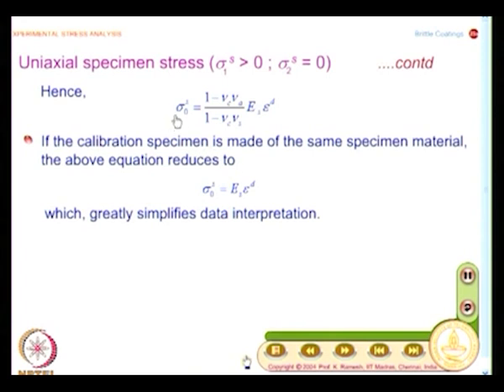So, what you have here is sigma naught s is equal to 1 minus nu c nu a divided by 1 minus nu c nu s into Young's modulus of the specimen into failure strain epsilon d. This is simple to derive. I am skipping the mathematical steps. It is not difficult, you can go back and work it out, and this brings out the role of Poisson ratio mismatch. In this expression, you have Poisson ratio of the coating, Poisson ratio of the specimen, as well as Poisson ratio of the calibration specimen. And I said you can reduce the problem by having the calibration specimen same as the specimen material, then this equation reduces to sigma naught s equal to Young's modulus of the specimen into epsilon d.